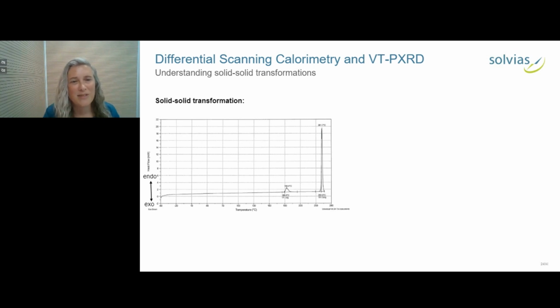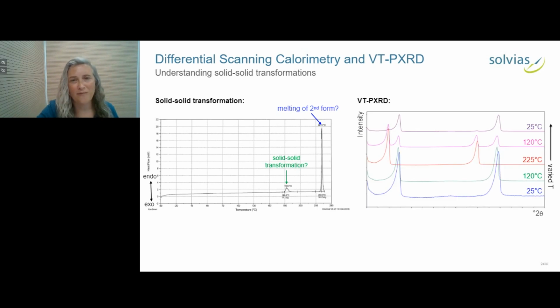Here you can see an example of a starting material that has 2 endothermic transitions. And an endotherm could correspond to a melt. It could correspond to a dehydration, desolvation event, but it could also correspond to a solid-solid transformation. And based on the position and the magnitude, that was the hypothesis. Here we had that the starting material transformed into a different form, and the melting point actually corresponded to the new form. And we were able to confirm this by doing variable temperature X-ray diffraction.